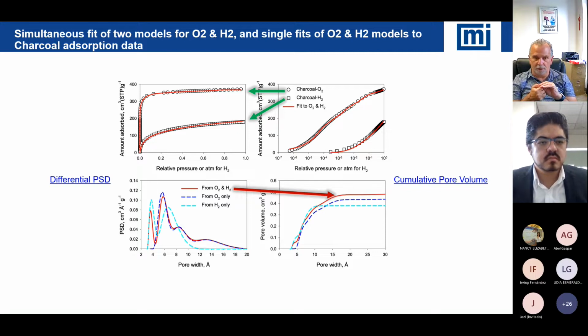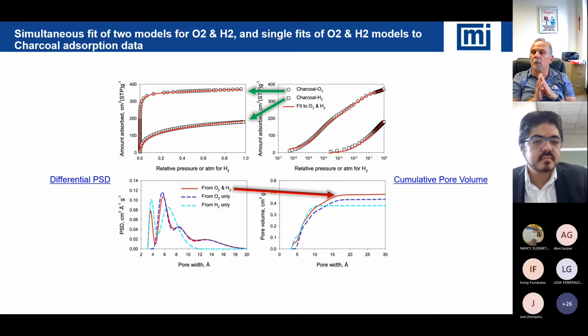So yes, your comments about the strange absence, we've seen exactly the same. When we've looked at it over the years, it gets back a little bit to the way you go from experimental data to pore size distribution and what's inside the model. It always gets back to older models where everyone assumed that the pores were homogeneous, that there wasn't any heterogeneity on the surface. Once we started introducing heterogeneity about a decade ago, this problem has become less severe.